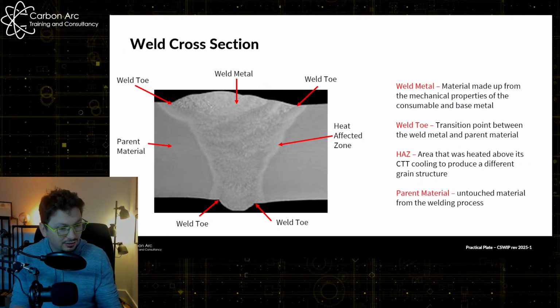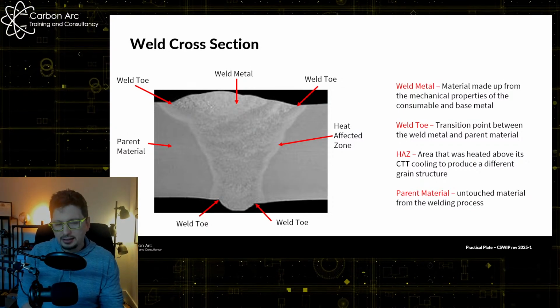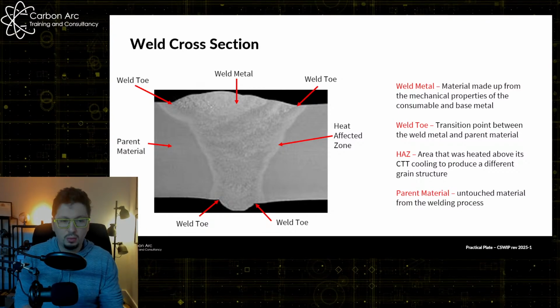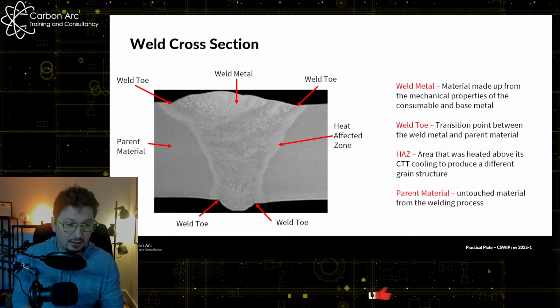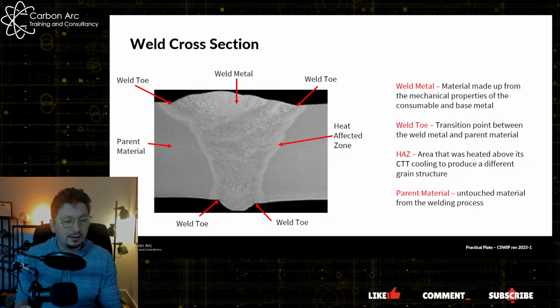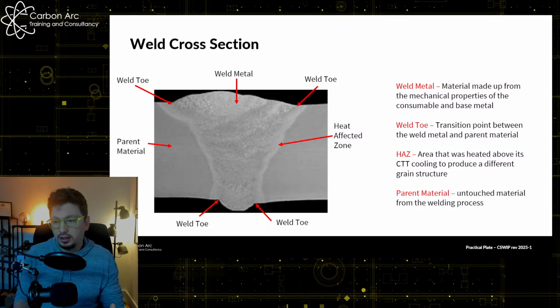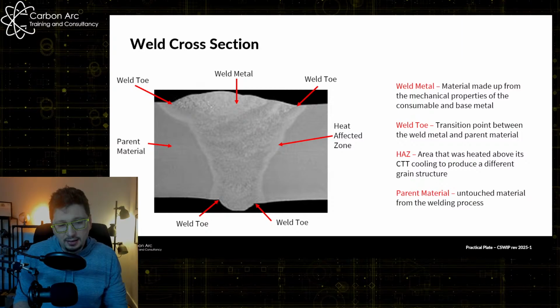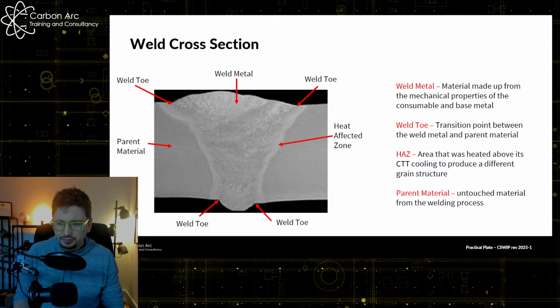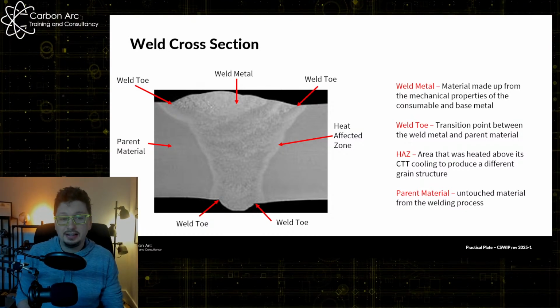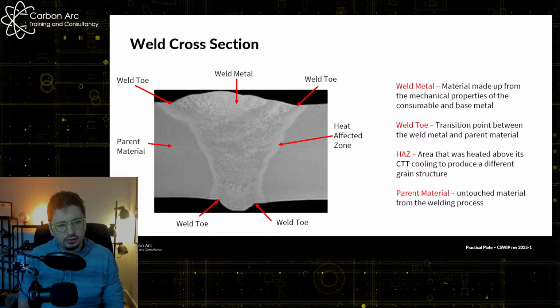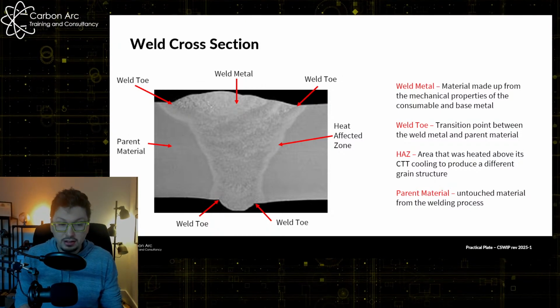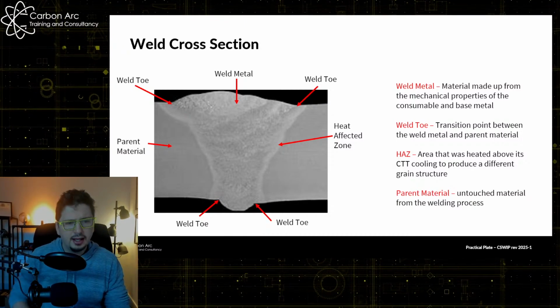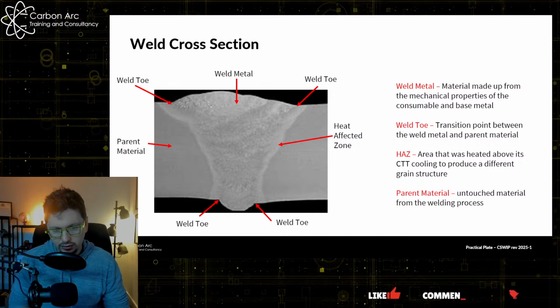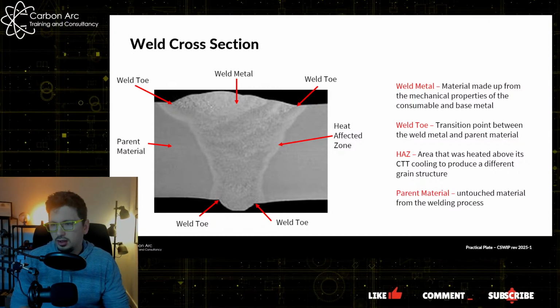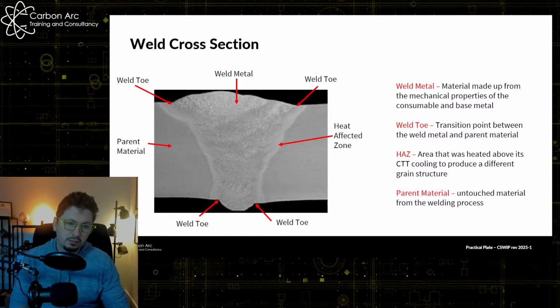What's a macro section? It's a relatively low magnification look at the weld, normally between 2 to 10 times magnification. The idea here is we're looking for welding defects in areas that we may potentially have imperfections within. You can often see the parent material, the heat affected zone, and the weld metal, but you can't see the grain structure. That's a micro examination, and micro exams are done at much higher magnification levels, depending on the material we're doing. It could be 2,500, 3,000 times magnification. But using this macro here, we can identify a couple of different places.